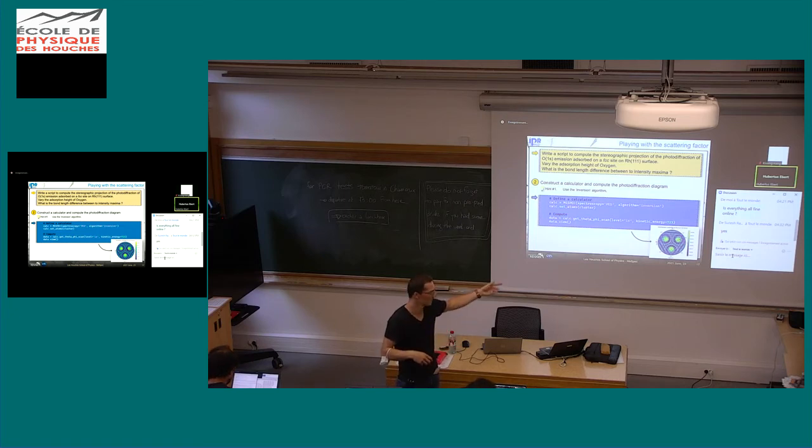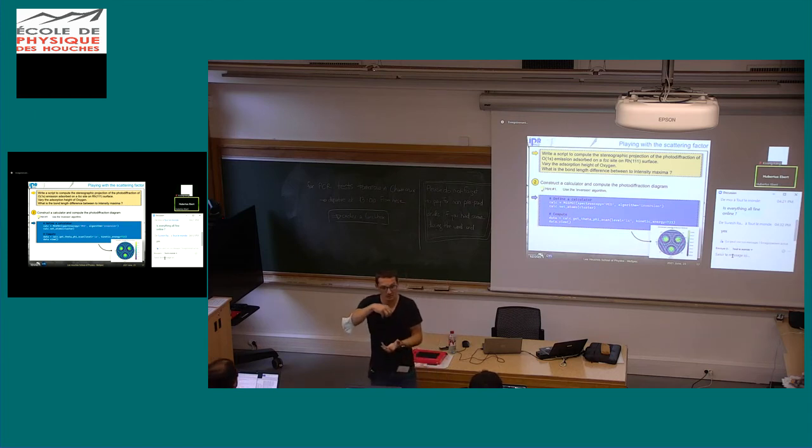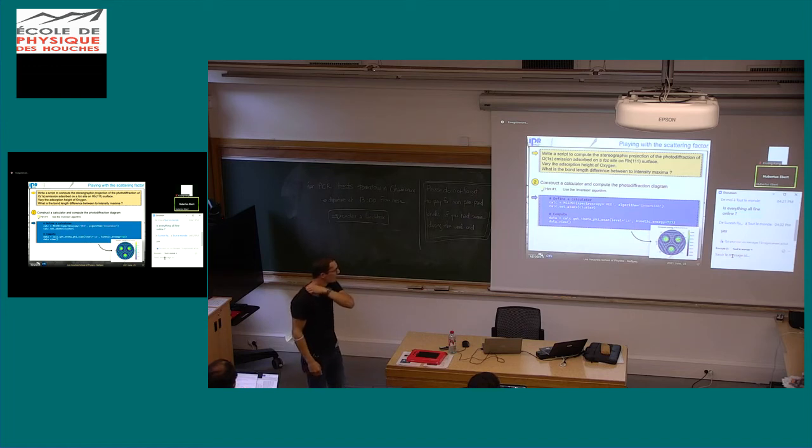So you will have 10, for example, stereographic projections, each corresponding to a different height. When you see that for one height of the oxygen there is a minimum of intensity, you will monitor the other height of the oxygen giving rise to another minimum of intensity. And the difference between those two heights, this is the number that I am looking for. How far should I move my oxygen atom between two maxima or two minima?